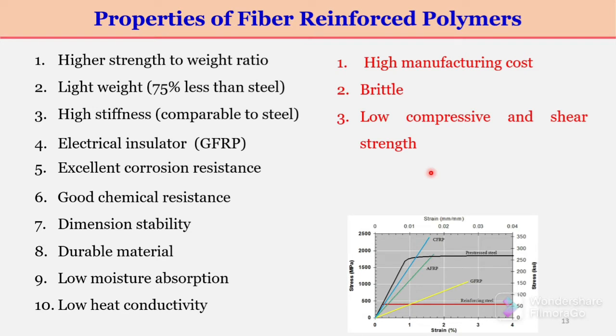They have low compressive and shear strength. As I said earlier, their strength is more in the direction of fibers, but perpendicular to that or in any other direction their strength will be less. So under compression as well as under shear, these FRPs are not that strong as they are strong in tension. And one more drawback or disadvantage of this FRP is that their matrix degrades due to ultraviolet radiation. This is a durable material, but the only problem is their matrix can degrade due to the ultraviolet radiations.